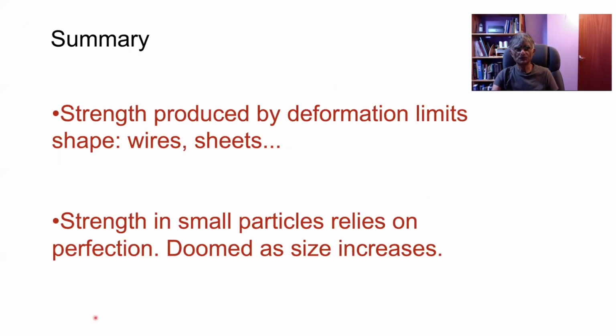Okay, so strength produced by deformation limits the shape, and the shape may be in the form of wires or very thin sheets because you have to deform a lot. And strength in small particles relies on perfection and is doomed as size increases. And we've known that for more than half a century, and yet people just do not learn that lesson when they make awful claims about the properties of small samples.